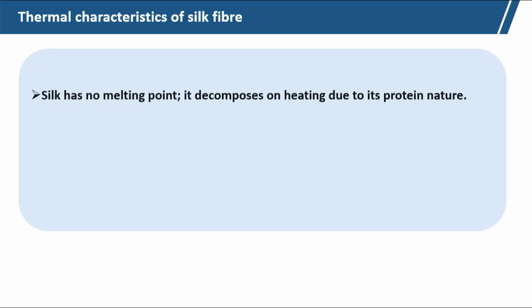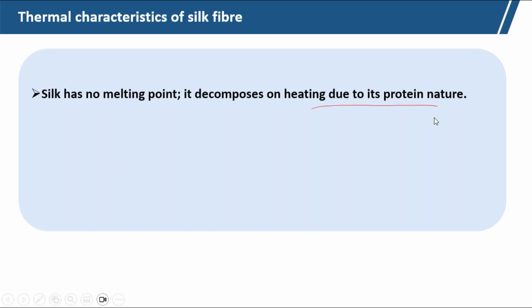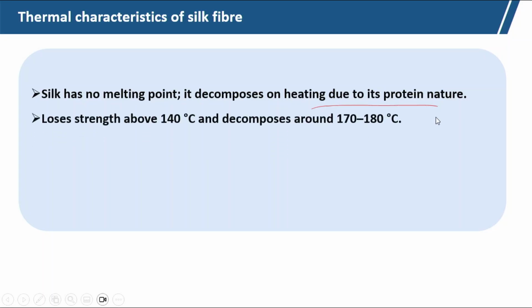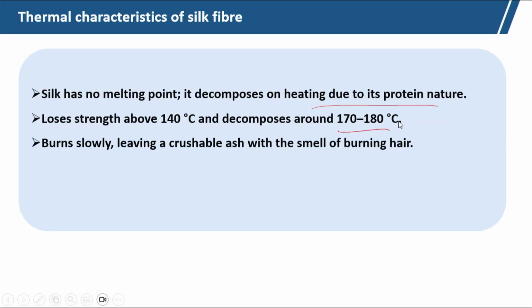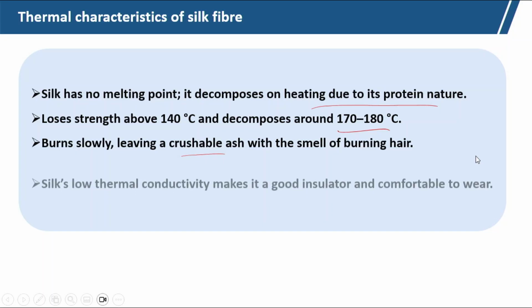Now, thermal characteristics. You can see silk has no melting point and it decomposes on heat due to its protein nature. It loses strength at 140 degrees Celsius and decomposes at 170 degrees Celsius. So, we can use silk fiber for low temperature application. It burns slowly and leaves crumbled ash with a smell like burning hair,